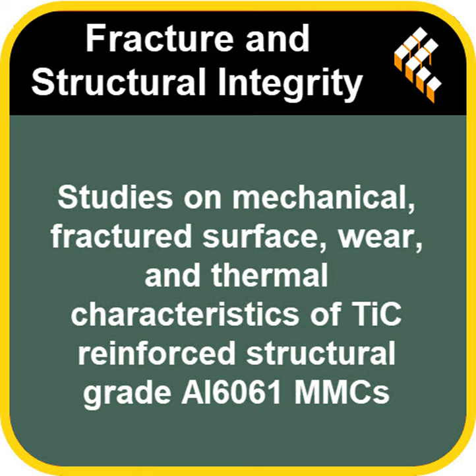Okay, multiple mechanisms at play. Right. They contribute to a greater load-bearing capacity, essentially helping the material resist being scraped or ground away. In fact, they can even act as sort of micro-abrasives themselves, but in a good way. They can help form a protective layer under stress. A protective layer, how does that work? It's thought that under the pressure and friction of wear, some debris might mix with the TiC in the matrix to form a hard, stable layer, sometimes called a mechanically mixed layer or tribo layer. This layer then protects the bulk material underneath.